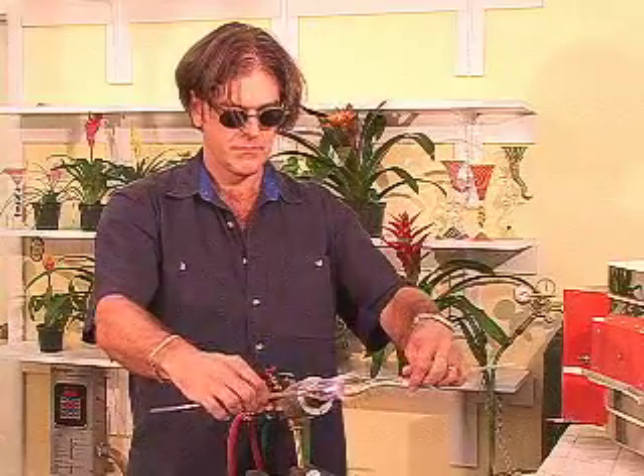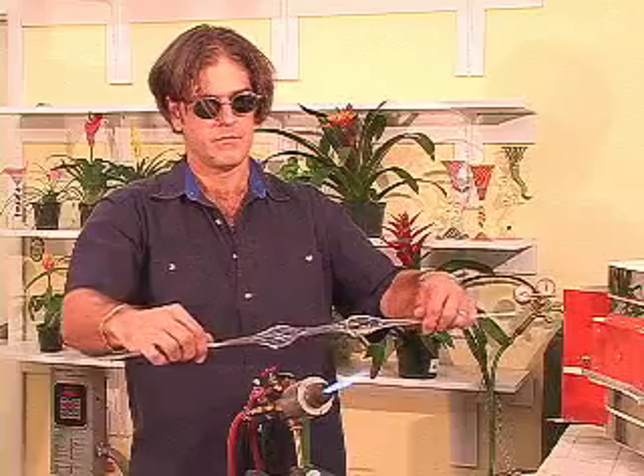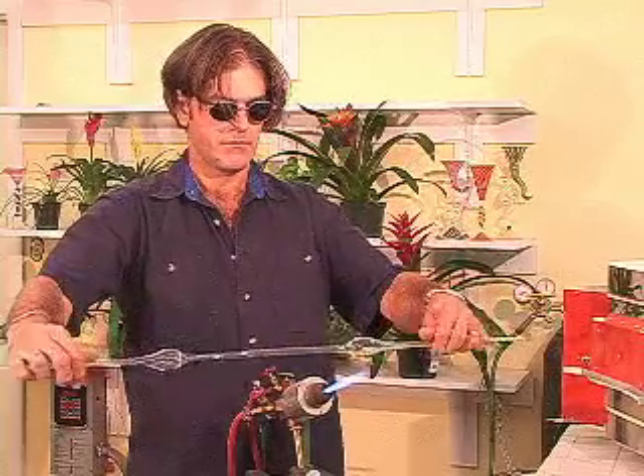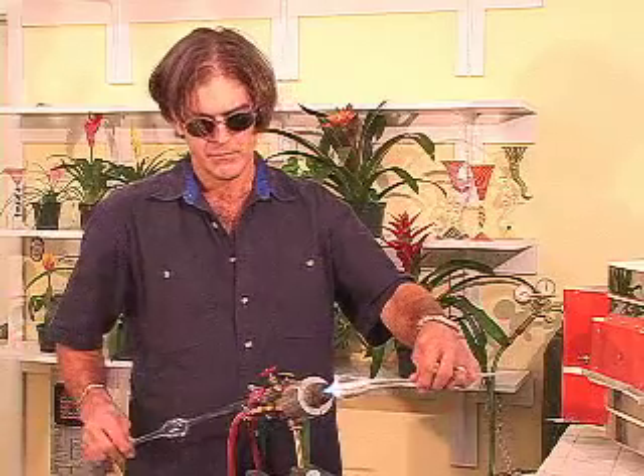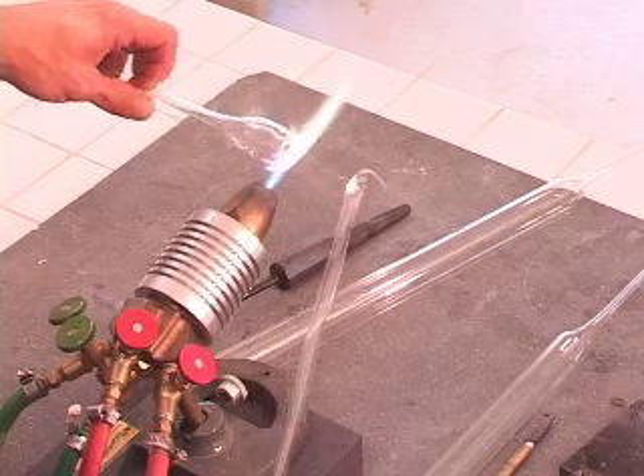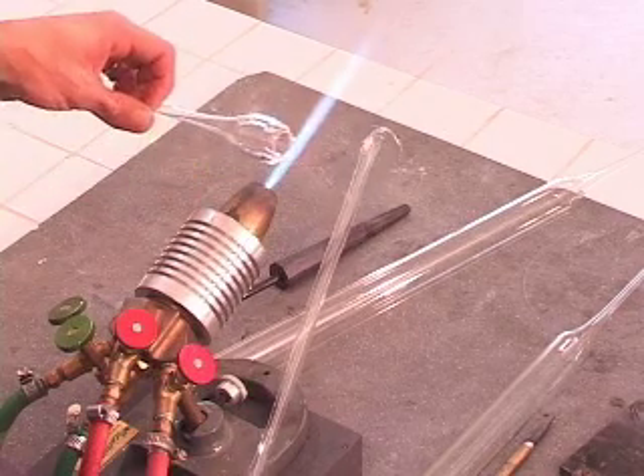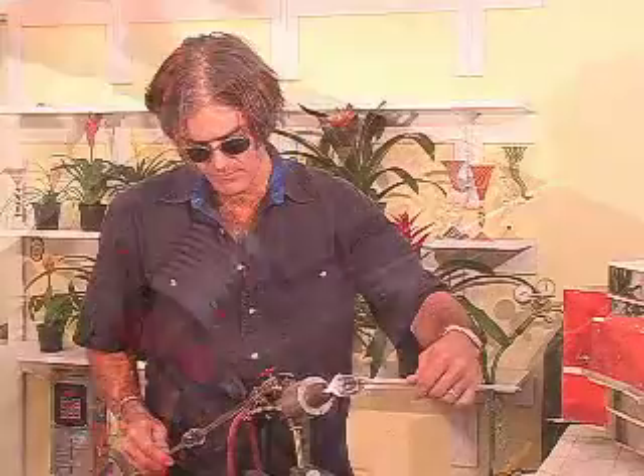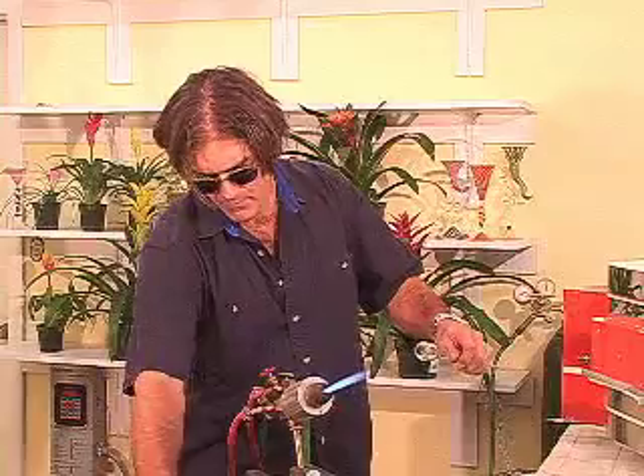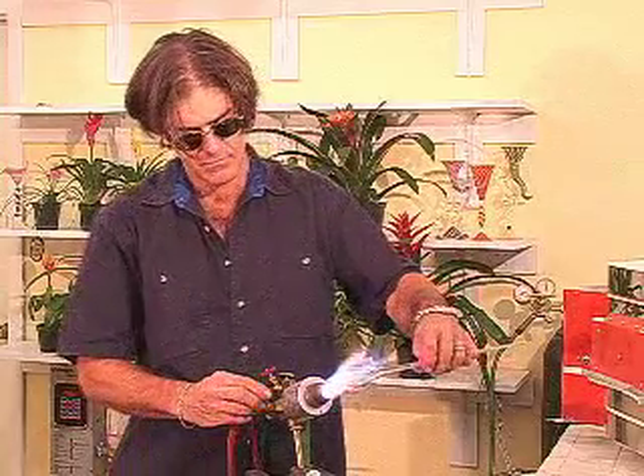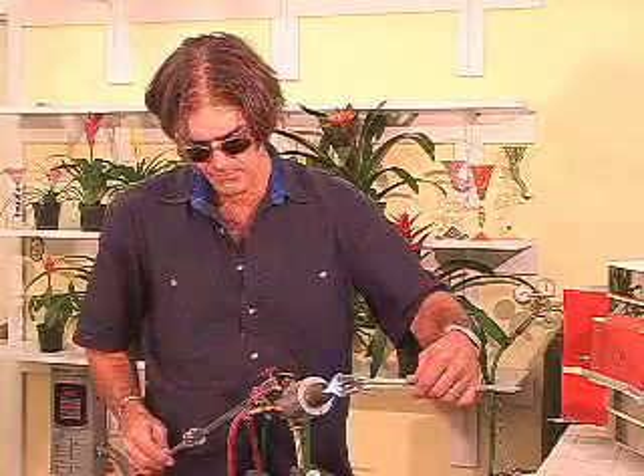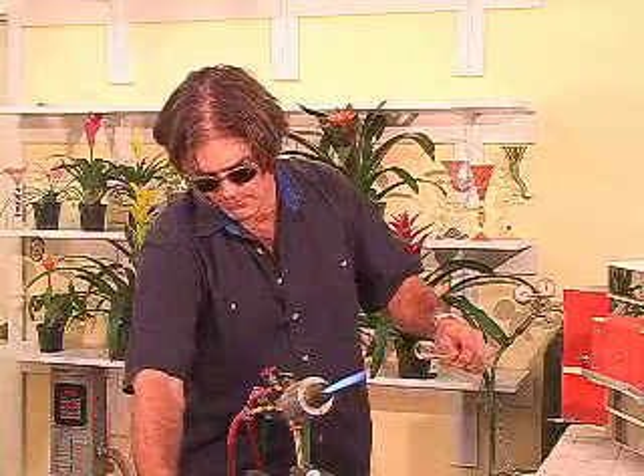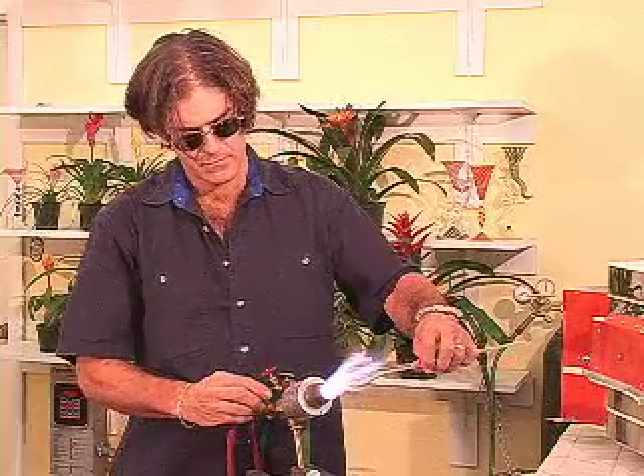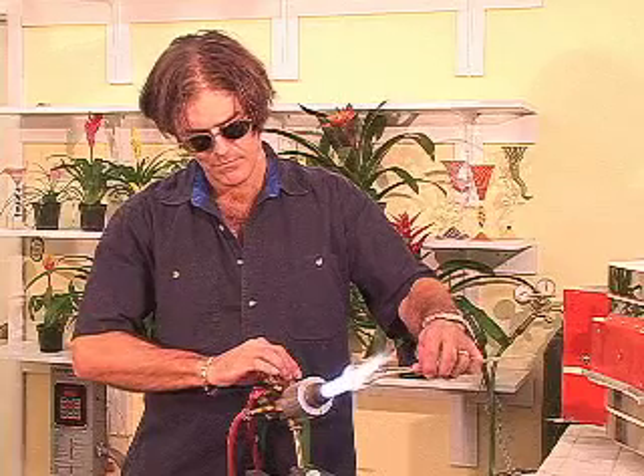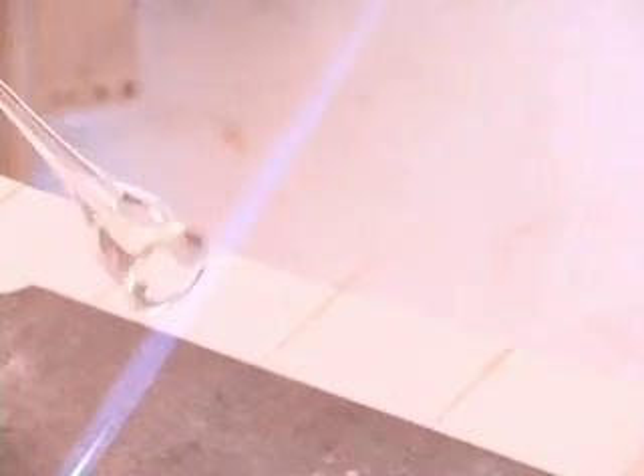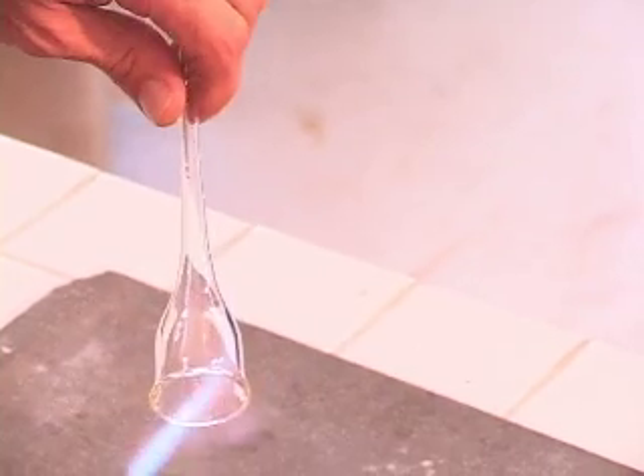First you must open one end of the tubing by scoring and breaking off the tip. Then heat up a narrow section and pull a thin point. Flame cut it at the shoulder of the closed point. Flare open the lips slightly using a graphite reamer and preheat the inside of the tubing.